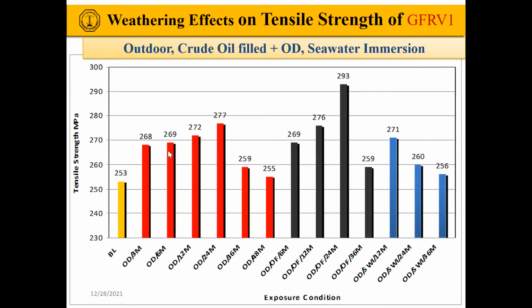As you can see, the longer the exposure, the higher the tensile strength. So the outdoor exposure is actually improving the tensile strength of the material. The same, you can see it for the oil filled, and to some extent also for seawater immersion. Why is that happening? We have observed that TG was increasing with exposure time.